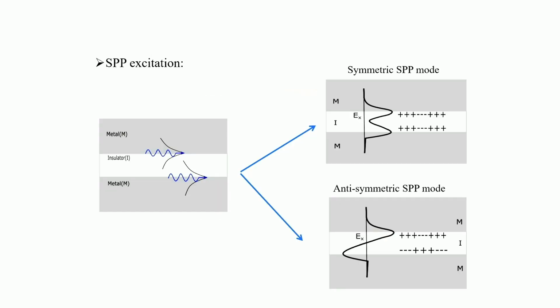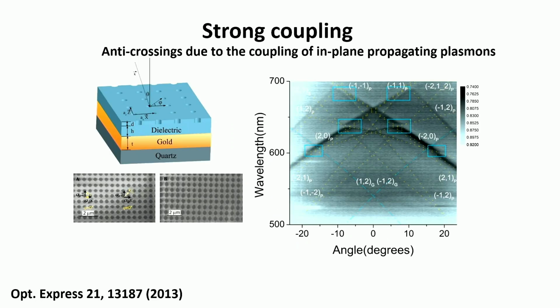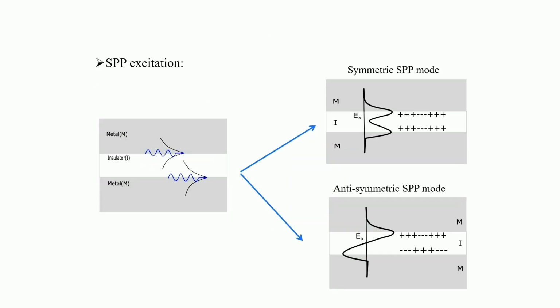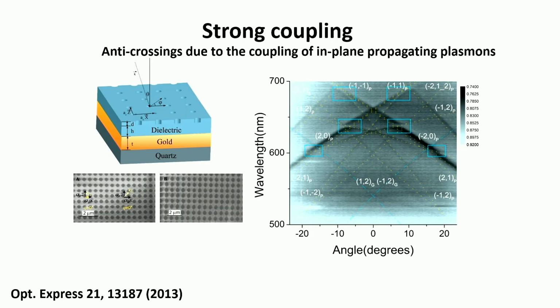But an interesting thing, from a physics point of view, is that if you have a metal-dielectric-metal structure or a dielectric-metal-dielectric structure, depending on the thickness of the middle layer, you can have coupled modes of these surface propagating plasmons at the top and the bottom. These can combine, and you can have symmetric and antisymmetric modes. These modes can interact with each other like any other particles we know of, and that is shown here.